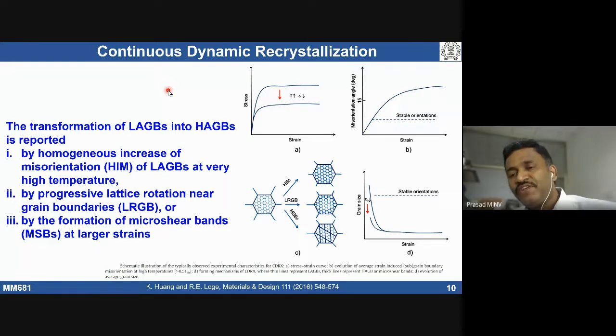See, if we talk about high stacking fault energy materials, they will undergo recovery fast. Am I right? Because cross slip is very easy, so dislocations of opposite sign can come together and get annihilated very easily as compared to low stacking fault materials. Okay, so the driving force for recrystallization: we want to have a recrystallized grain, we need some driving force for a new boundary to form. Dislocation density is supposed to be the driving force. But if dislocation density has already come down because of recovery, where is the driving force for recrystallization to happen in high stacking fault materials? Is there any driving force left?